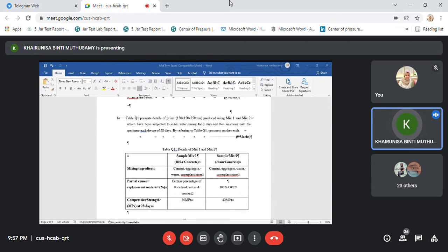Lepas tu ada juga yang cakap the use of rice husk ash which has too little content of silicon dioxide also affects the performance of the concrete. You boleh juga cakap probably because of the rice husk ash which has been used is a coarse size. Maknanya size dia kasar. So when the coarse size is used, it will affect the pozzolanic reaction. Sebab dia kasar kan, so reaction tak boleh nak berlaku lah, ataupun the rate of reaction is very low. Okay, so it will affect the strength of the concrete.